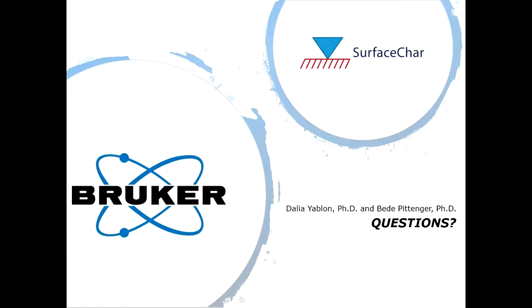I don't know, Bede, do you want to add anything more? Yeah, I'll add a couple of things. One is, when you see loss tangent calculated using one of these methods, since the models these multi-frequency methods are using don't include adhesion, they have a tendency to incorporate adhesion into the measurement in unexpected ways. For example, loss tangent typically ends up being significantly higher, by factors of 2 to 5, than what it should be, even with a time-temperature translation to the right frequency. So there are definitely some issues with making a quantitative comparison that go beyond just the frequency problem, which is definitely an issue as well.